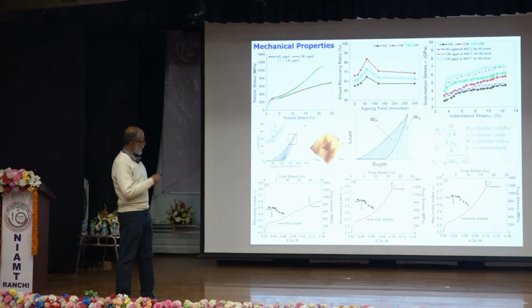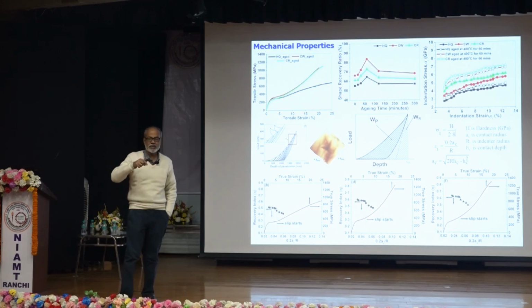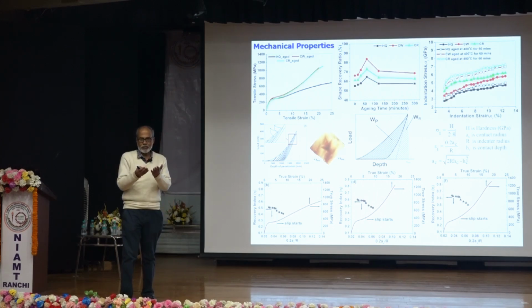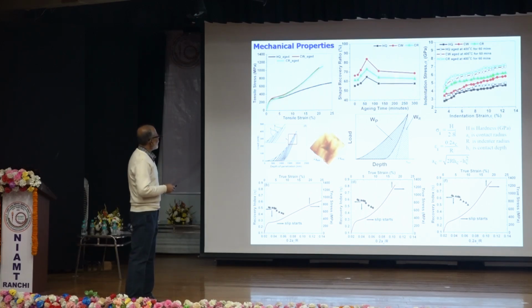And as I have mentioned in the title, we observed the shape memory behavior of individual martensite plates by nanoindentation. We put it under microscope. And we have taken the indentation on several martensite plates of comparable size. What do we find? This is the stress strain behavior. And for nanoindentation experiment, you can measure stress and strain by certain empirical relations proposed by Tabor, right? Where H is the hardness, AC is the contact area. It is done by a ball indenter and cyclic loading mode. Someone who is familiar with nanoindentation technique can get it.